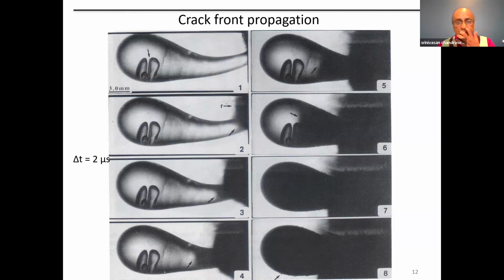These drops were speculated, based on rigorous theory, to have tensile stresses in the interior and compression in the outer region. So the core is conducive to crack propagation, and people knew that there was tension in the interior and compression on the outside, so the crack would propagate in the core.